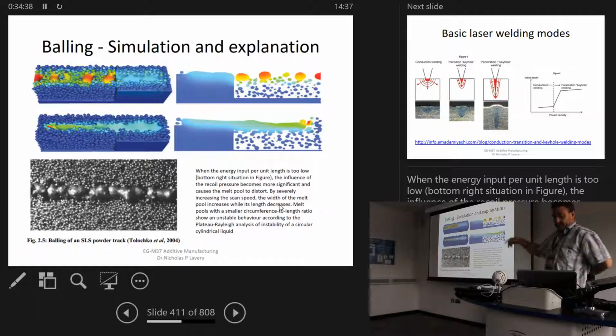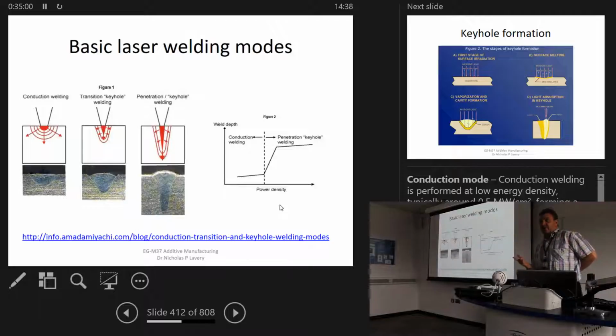There's a lot of work going on trying to simulate this kind of stuff, and we're doing some of this as well. But these results are actually from Lawrence Livermore, and you can see there a higher power, higher speed, continuous laser. You can see one at the top where you've actually got that balling effect coming up on the powder. So that was one of the instabilities related to laser melting of powders, which is the balling instability, the Plateau-Rayleigh instability. And that leads to balling, so basically it's an instability which is related to the longitudinal direction of the melt.